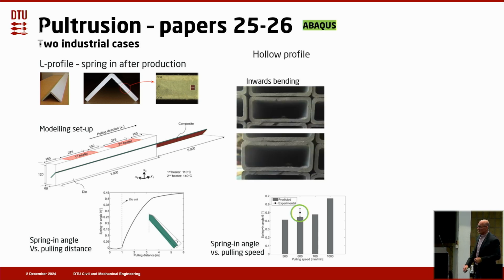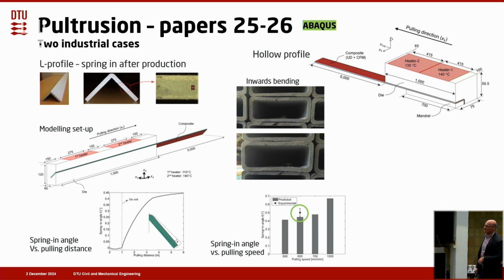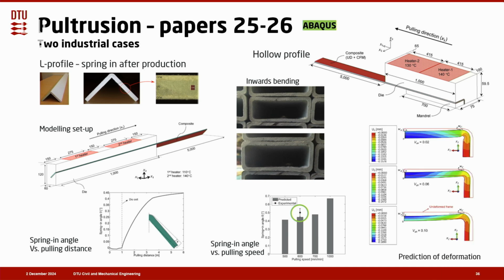Then there was another hollow profile that also suffered from inwards bending. You can see that there when they're put on each other. And then we were simulating that in a model. And this is only 1/4 of the model, but you see that it gives this inwards bending as well. So we could really use this thermochemical mechanical model for predicting final deformations.